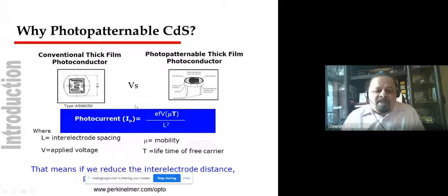The theory says that photocurrent is directly proportional to the intensity of excitation, applied voltage, and the product of mu and tau. Mu is the mobility, and this is not T, actually it's tau, which is the lifetime of free carriers. So it is directly proportional to this product, mu and tau, but inversely proportional to the square of the interelectrode distance. If you keep on reducing the interelectrode distance, probably you'll get the maximum photocurrent. But this is a surface electrode structure. If you indefinitely reduce the interelectrode distance, you'll not find any place for cadmium sulfide, which is available as photon catchment area. Where is the photon catchment area? Maybe you have a zigzag structure, but that's also not really useful.